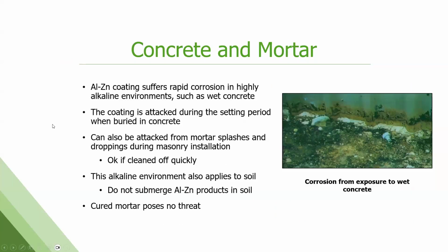Concrete and mortar and the Galvalume product don't like each other. Again, because of the moisture that's in the cement as it's setting up to become concrete, very alkaline, very destructive. It's an example of a wall panel that was just set right on the concrete foundation without any kind of barrier there. And you get this really nasty edge creep that occurs. But if you put a barrier in there, you're fine.